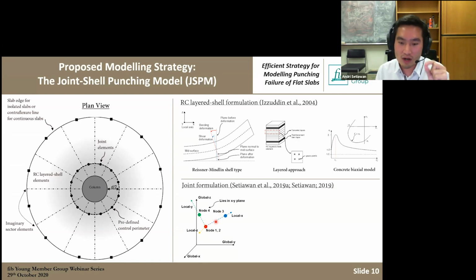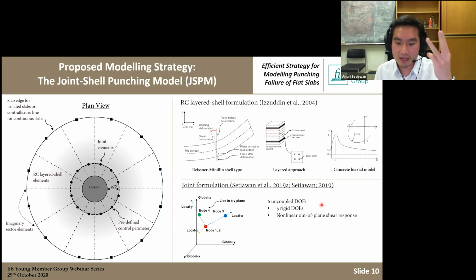I will explain to you one by one what is the function of each node. So this joint has 6 degrees of freedom, 3 translation and 3 rotation. We assume that all the other 5 degrees of freedom, except the out-of-plane shear, are rigid. So we ensure a compatibility of the shell itself. But for the out-of-plane, we impose a certain constitutive behavior in order to be able to capture punching. So it's like, let's say, a 1 degree of freedom joint spring at the end.